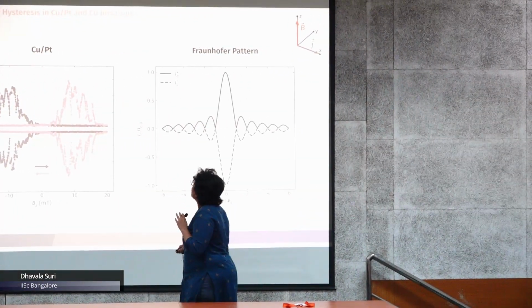So this is a planar Josephson junction where the two niobium electrodes are separated by about 15 to 20 nanometers. Now if you go farther, you may be able to do exactly what you are saying, but then the coherence length is very, very small. So you can't go farther at all to get the Josephson current in the first place.